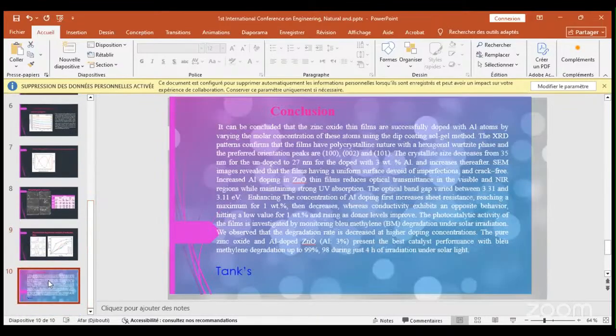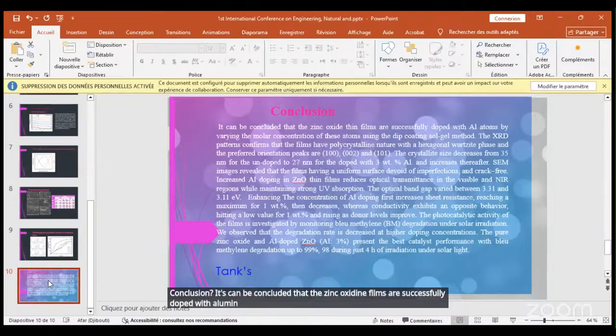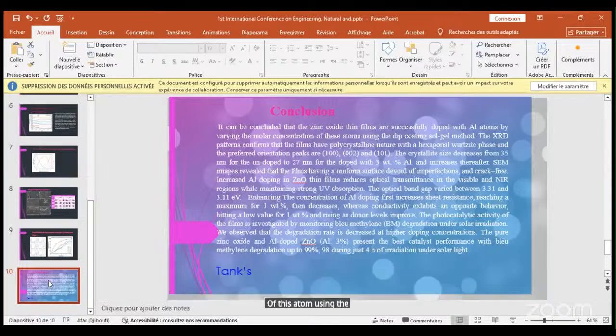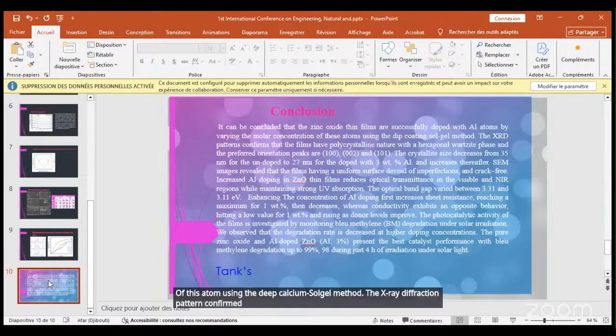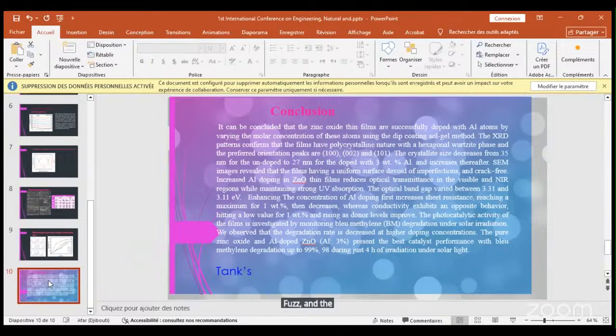Conclusion. It can be concluded that the zinc oxide thin films are successfully doped with aluminum atoms by varying the molar concentration of this atom using the dip coating sol-gel method. The X-ray diffraction pattern confirmed that the films have a polycrystalline nature with a hexagonal wurtzite phase, and the preferential orientation peaks are 100, 002, and 101.